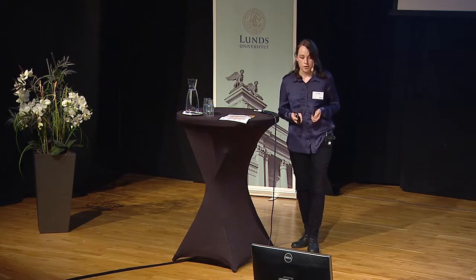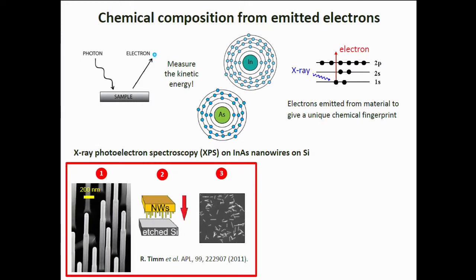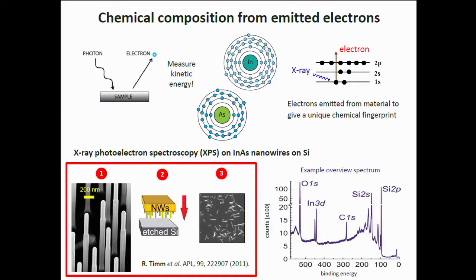This technique is called XPS — X-ray photoelectron spectroscopy — and we can perform this on our nanostructure devices, in particular nanowires. We take our nanowires as they're on the as-grown wafer, break them off, and put them onto a different type of material. For three-five nanowires we would usually use a piece of silicon. We then have a sample containing many nanowires randomly oriented across the surface. When you irradiate that with light, we get our complicated chemical fingerprint. This is quite a complicated spectrum, but the different peaks can be attributed to different species in your nanowires and also the underlying silicon substrate.